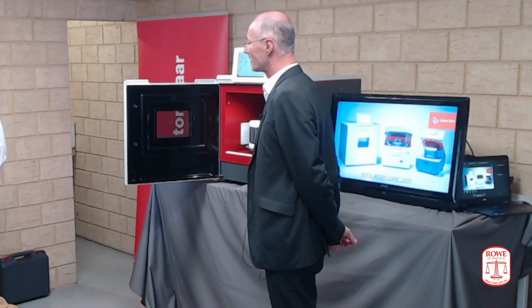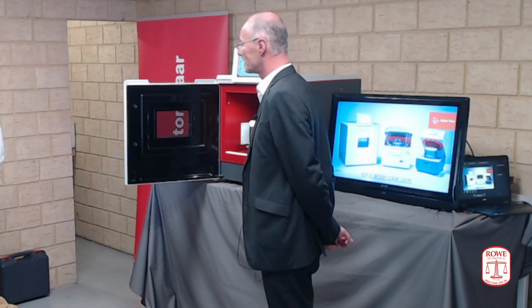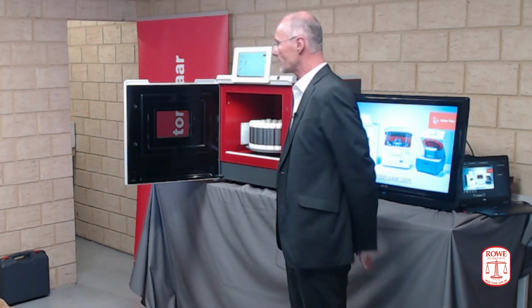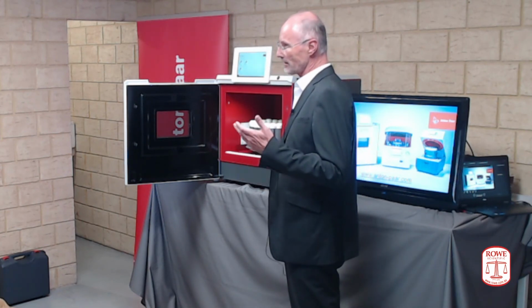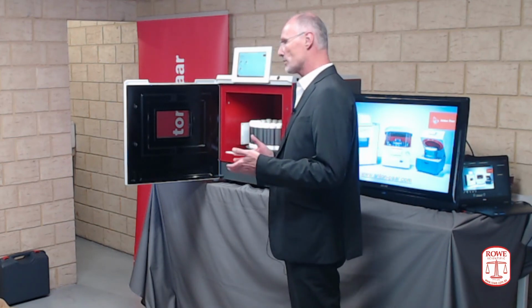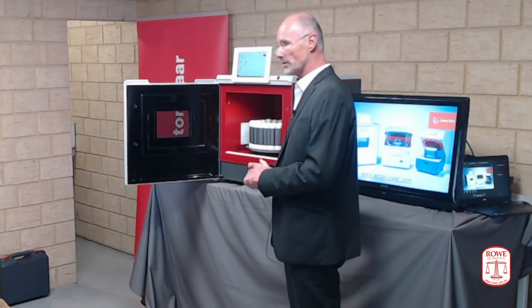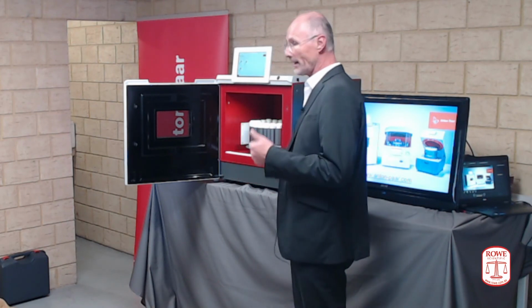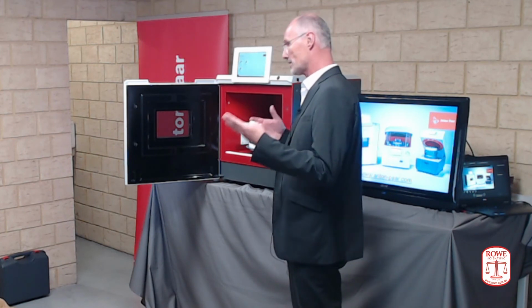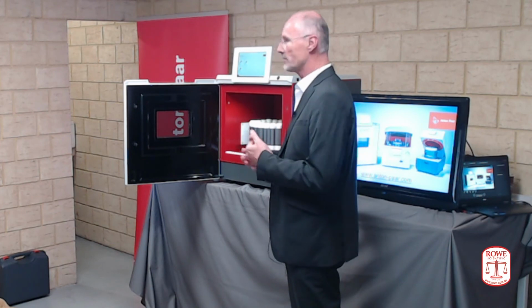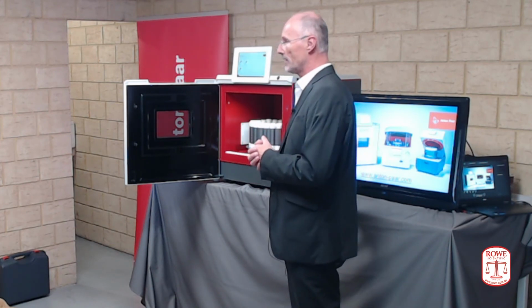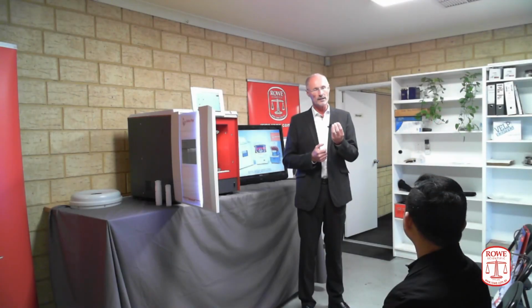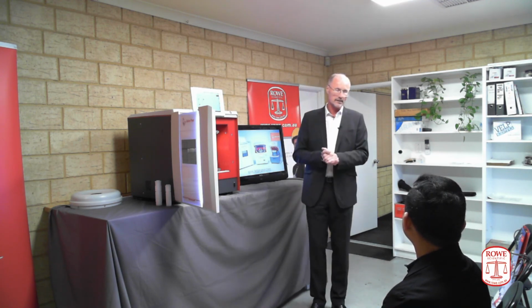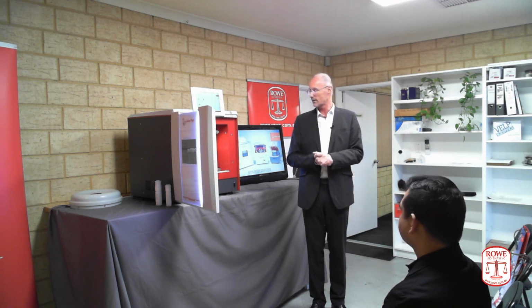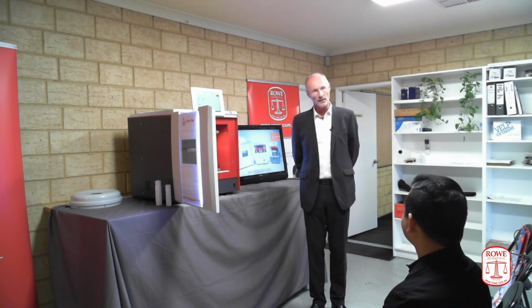In terms of the digest vessels and rotors, do they degrade with the number of cycles they go through the microwave? Okay. Question was, do vessels degrade depending on the number of cycles? Of course they do, and it depends on the reaction conditions. If you digest, let's say, food samples with nitric acid, you can run maybe thousands of samples before you replace a vial. If you do high temperature digests at 250 degrees with this 4-acid digest, including sulfuric acid, vessels will wear out faster and maybe last only a few hundreds of runs. You could detect this when the inner surface of the vessel changes, when it gets rough and particulate. This is the time when you see you have to replace the vessels. They have a limited but very long lifetime.